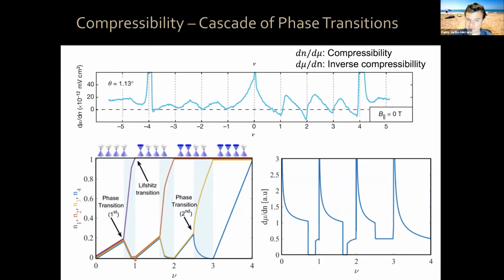Then the same process starts again. I start filling the other 3 flavors, close to nu = 2. The system decides to, again, spontaneously flavor polarize, polarizing 2 flavors, and then 2 of the flavors become empty, etc. These phase transitions that take place due to strong electron interactions form this cascade at each integer. And in a simple model, you can see that this gives you an inverse compressibility which has a sawtooth type of behavior, okay? There are more refined models nowadays that account better for this behavior, but the essence is a sequence of phase transitions due to strong electron interactions, which lead to flavor polarization of your bands, okay?